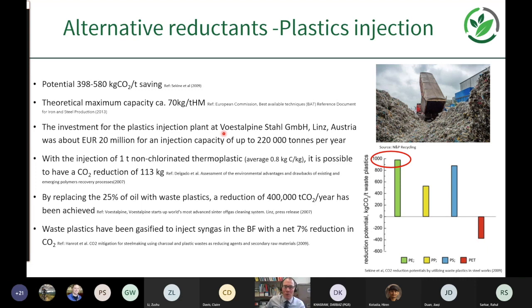So what I've been looking at more recently is the use of plastics and potentially biomass, paper, in reducing the CO2 emissions. And the importance of this is that potentially there's room to improve the CO2 emissions from plastics injection. So not only are you repurposing the blast furnace, not only are you utilizing material that otherwise might find its way into landfill, but you're also substituting, importantly, mined coal. And in the process, you're improving the CO2 savings per ton of hot metal, per ton of plastic that's injected into the furnace.